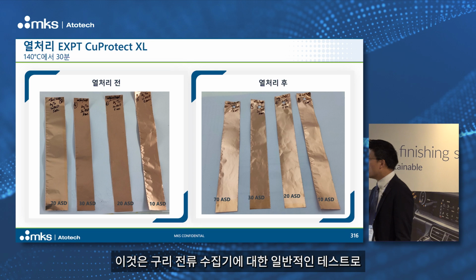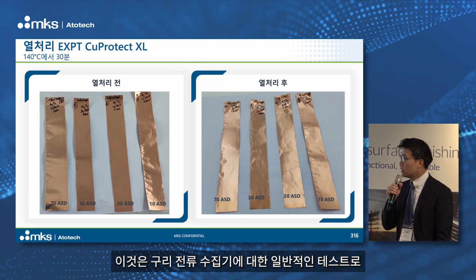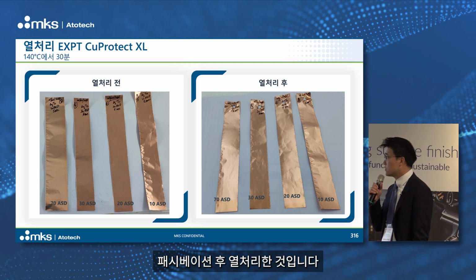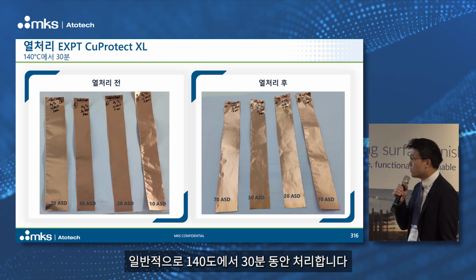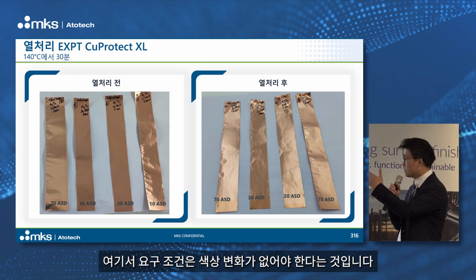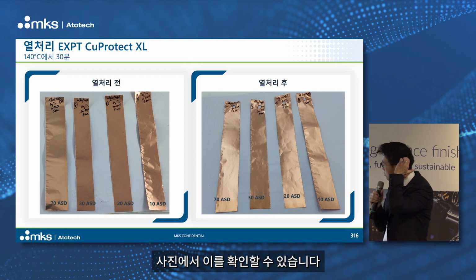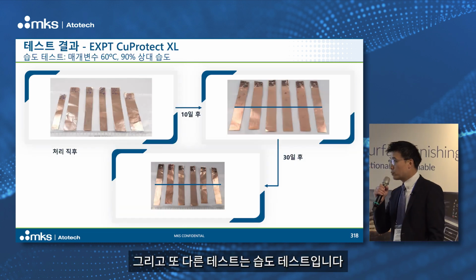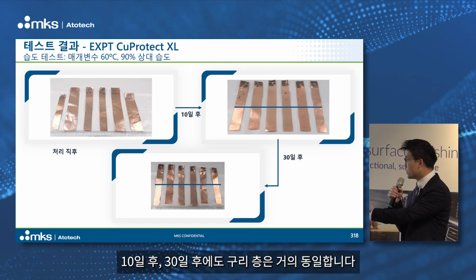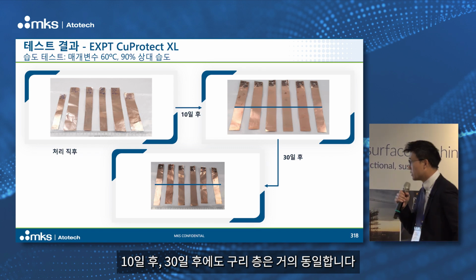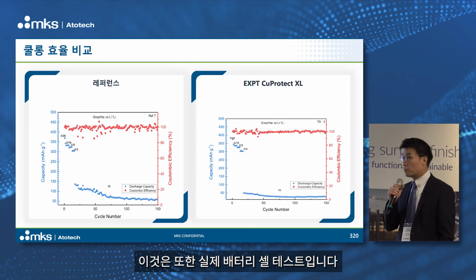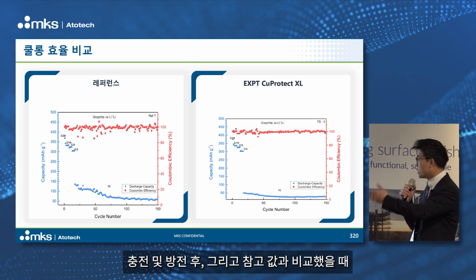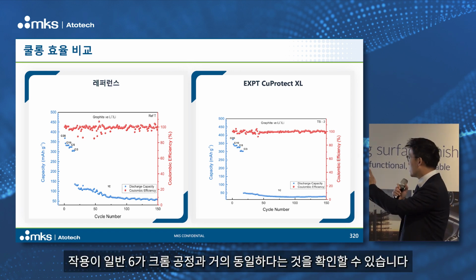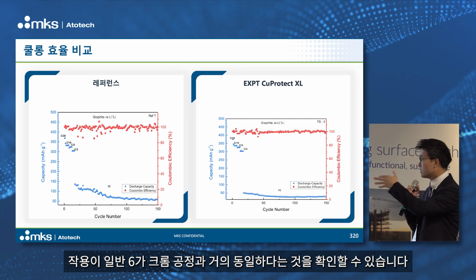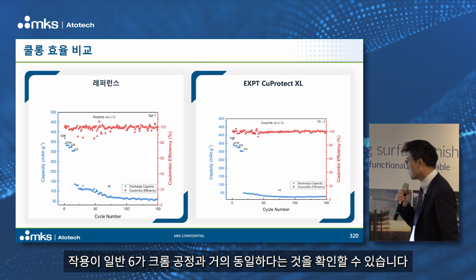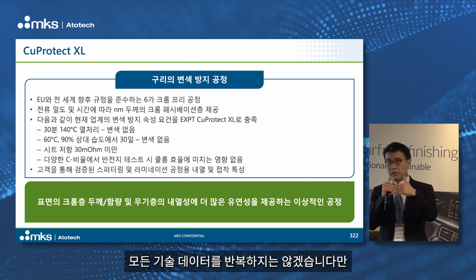So this is a normal test for a copper current collector, which we call heat treatment after the passivation. Normally it's 140 degrees for 30 minutes, and the requirement is that there's no color change, and you can see that in the picture here. And this is another test, which is the humidity test, and you can see after 10 days, 30 days, the copper layer is almost the same. And this is also a real battery cell test, and you can see after charging, discharging, when we compare with the reference, the behavior is almost the same as the reference, which is the normal Chrome 6 process.